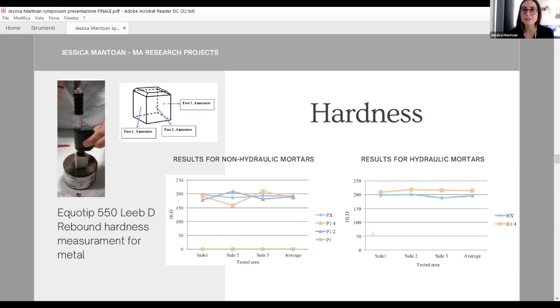Completely different results are shown for hydraulic mortar, where the samples containing barium hydroxide additive result, on the opposite, harder with respect to the control sample.